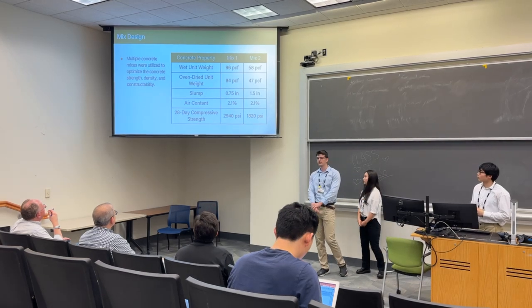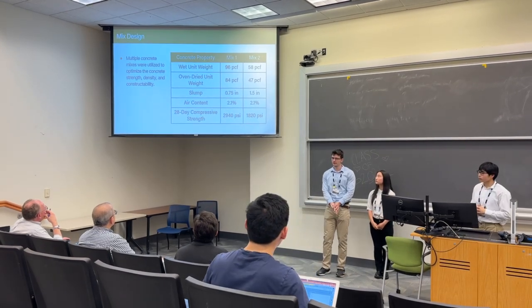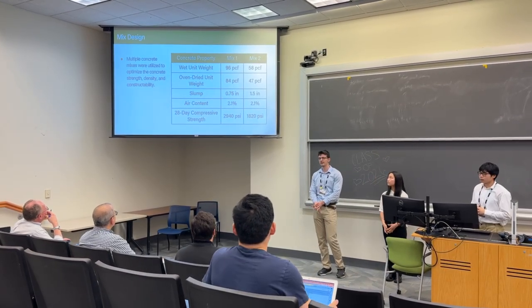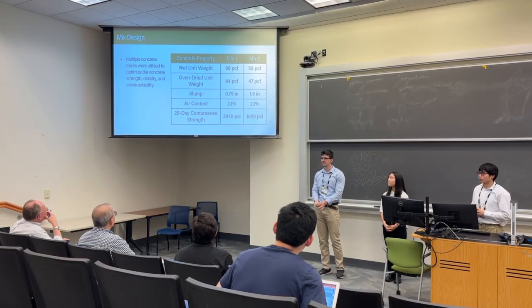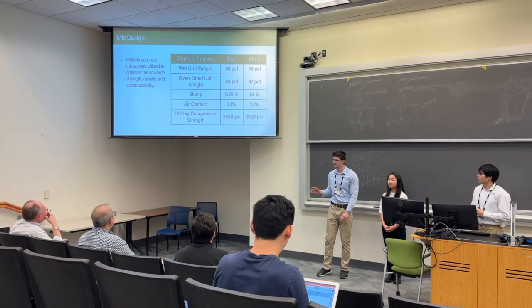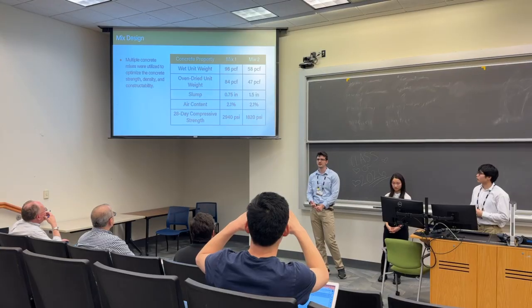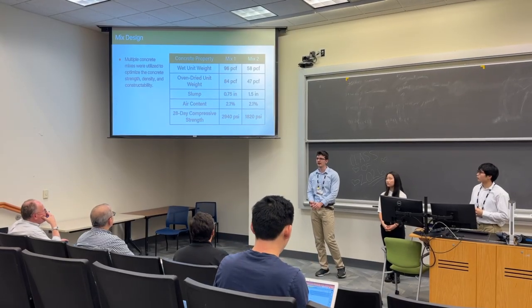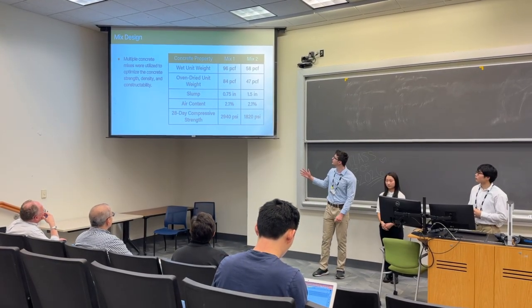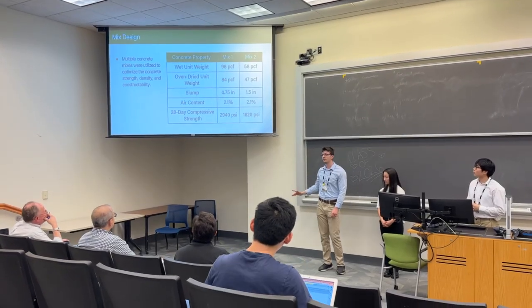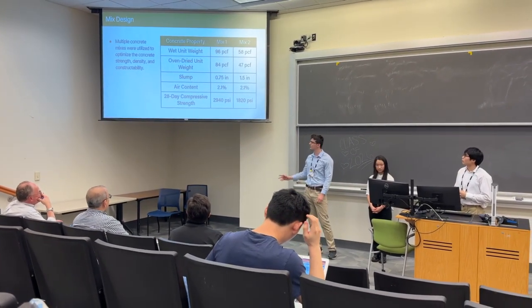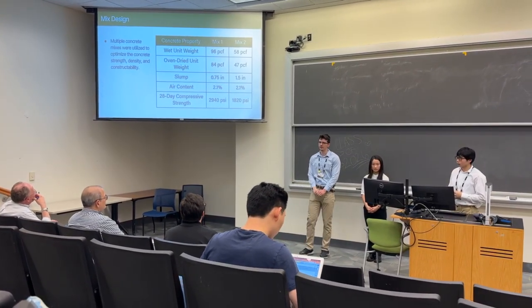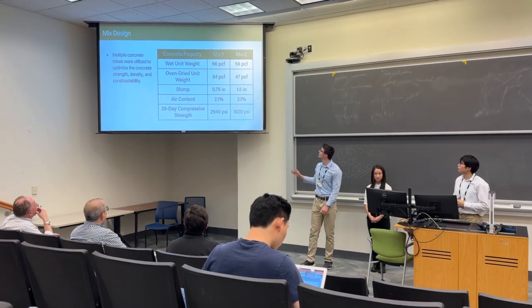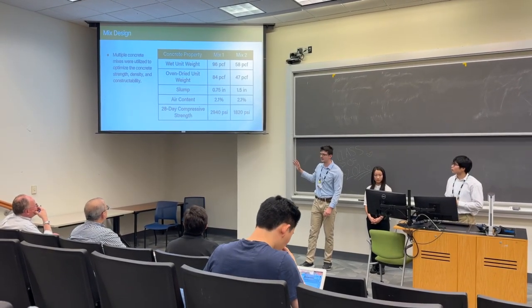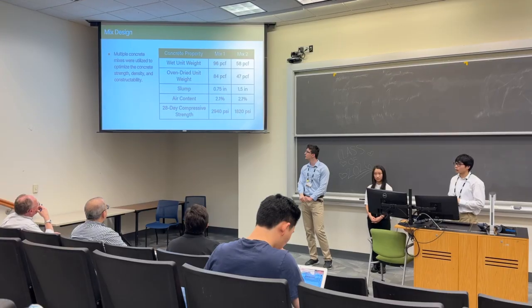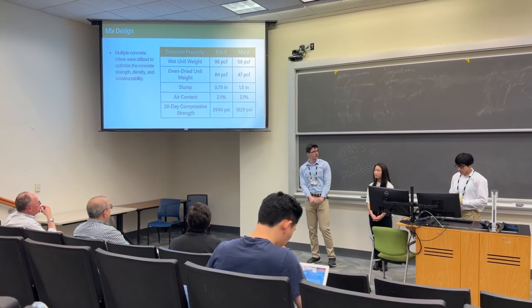Alright, so the main goal for the mix design this year was to create a stronger mix compared to previous years, while also having a more environmentally friendly design. This occurred by using new cementitious materials such as Type 1L and slag cement. And as you can see in the results here, we have a wet unit weight for mix 1 of 96 PCF and a strength of 2940 PSI. This is the highest in the program's history. And then for mix 2, we had a much lighter mix with a final strength of 1820 PSI, which is also stronger year over year.